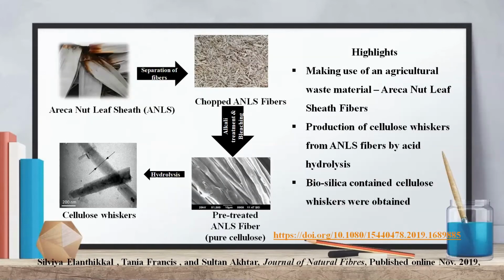This was actually the highlight of the work, to make use of an agricultural waste material like the arecanut leaf sheath fiber and to produce a value added material like a cellulose whiskers, which can find a large amount of applications in various industries. So the first part of the processing was to separate the fibers, chopping the ANLS fibers, subjecting them to alkali treatment and bleaching. First, we were able to extract out pure cellulose. And then this pre-treated ANLS fiber was subjected to hydrolysis using acids of various concentrations. And we were able to optimize the procedure, and we could get cellulose whiskers with biosilica embedded in them.